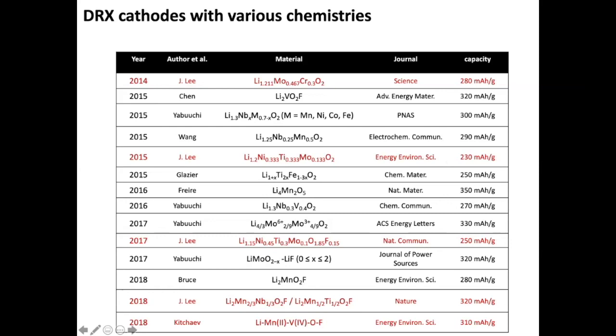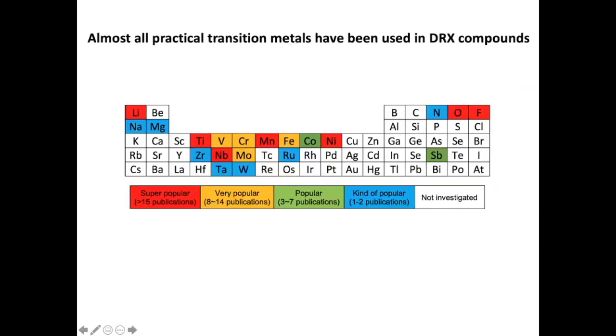There's been lots of material studied now. And again, our first aim is kind of achieved here, right? There are very diverse chemistries in play. And actually we did a recent study of the papers published in this field, which is still very young. And the colored metals are all involved in these DRX materials. And what's kind of amazing when I looked at this, almost every transition metal that is practical has actually been used in DRX materials now. Almost all the 3Ds, all of the 4Ds that are reasonable, of course, we're not going to use technetium or rhodium or palladium or silver, and some of the 5Ds. So clearly, when you go away from the cation order, you can use lots of metals.